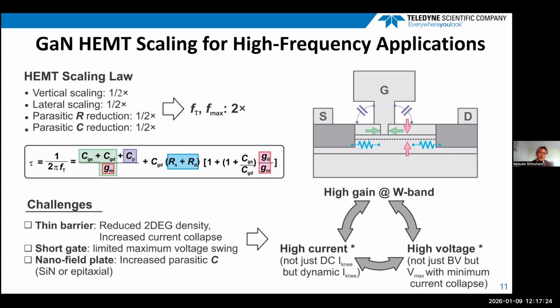And sometimes a nano field plate is very effective to alleviate the electric field, which, however, increases the parasitic capacitance. So achieving high gain at high frequency, such as W band, and high current operation and high voltage is very difficult because they are in a trade-off relationship. And I mean here by high current, not just the DC current density, but the dynamic current density. And similarly, I mean high voltage, not the breakdown voltage, but the maximum operational voltage with minimal current collapse.